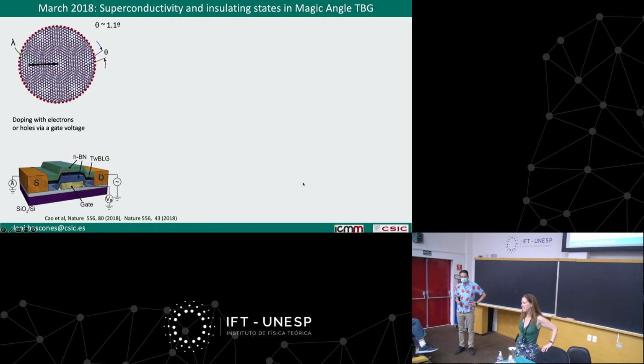Also, in some of the systems, even in the ABC trilayer without any moiré, the superconducting states violate the Pauli limit. So people believe that some of these states could be triplet. And in terms of theory for twisted bilayer graphene, all kinds of imaginable possibilities for order parameters have been proposed. People have talked about topological superconductivity. Yes, but all kinds you can imagine have been proposed.